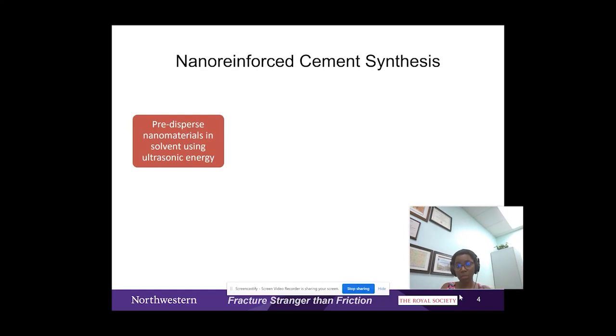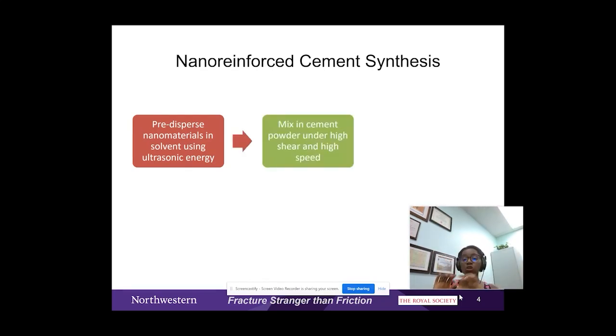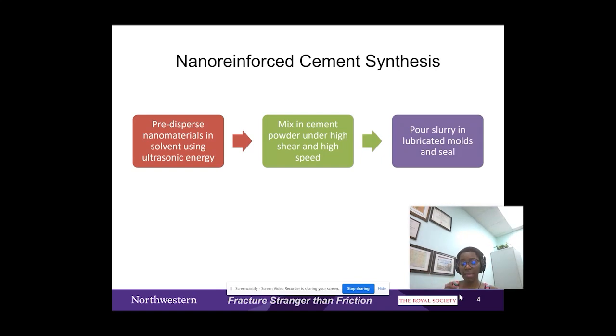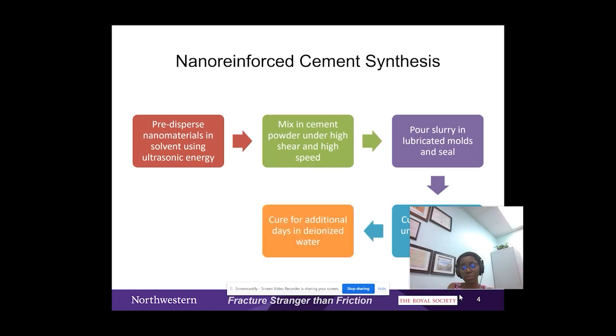using deionized water and ultrasonic energy. Then I'm going to mix that suspension using high speed and high shear, mixing it with cement powder. Afterward, I'm going to be casting it and using, in this case, mechanical stirring during the first 24 hours with an orbital shaker. And then I'm going to be curing for 6 days using deionized water.